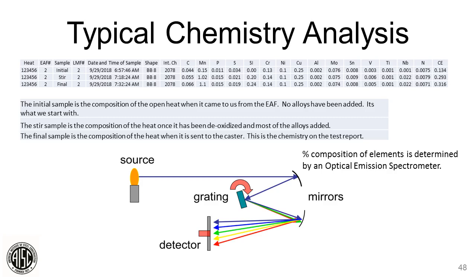So if you look at the very top here, we're showing you our process of a heat. If we go to the very top line of the chart there, heat 1, 2, 3, 4, 5, 6, there we go. It shows a sample initial, it goes to LMF2, and what I want you to look at is the carbon, manganese, phosphorus, and sulfur, not so much phosphorus, but those elements. As we process the heat, the carbon goes up a little bit, definitely the manganese goes up because we're trying to get the alloy additions in there to get the strength we want. Phosphorus in this one's pretty much staying the same, but the big one I like to see is the sulfur. You see the sulfur's being worked down.